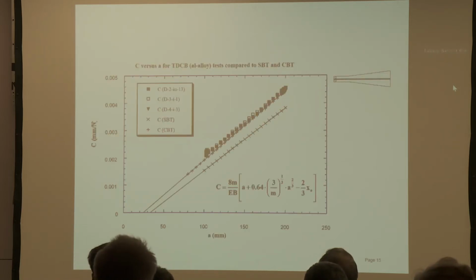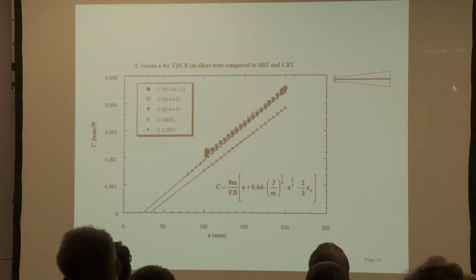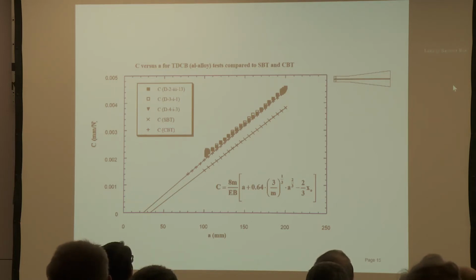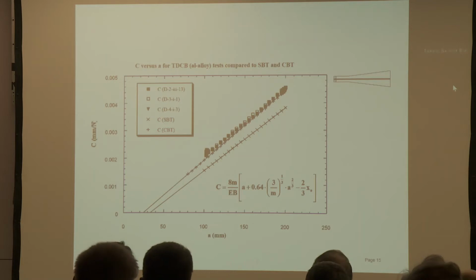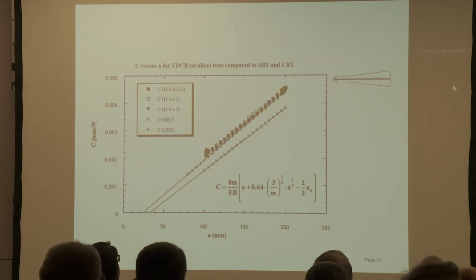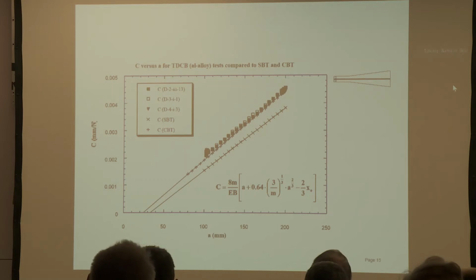So if one looks at the compliance against the crack length using, for example, the original simple beam theory, there was both an error in slope and an error in intercept based upon the original analysis. And when we were developing the ISO standard for the mode 1, we took those two terms into account, and we ran a series of round robins within the ESIS TC4 group to look at that effect and to work out the accuracy and the reproducibility. But that solution for the tapered double cantilever beam was successful.